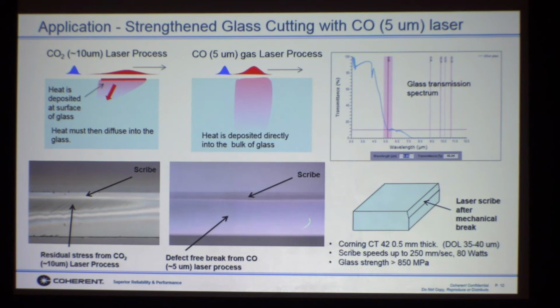These are some pictures of Corning, what everyone's calling Gorilla Glass. This is a very strong glass. The depth of layer is 35 to 40 microns. We're able to cut this at 250 or so millimeters per second with 80 watts. So this is not a real expensive laser, by the way. And you can see that it's perfectly clean, defect-free. And the glass strength, with the 4-point bend tests we've done, is all greater than 850 megapascals. So it's still very, very strong glass. That's one example of where CO lasers have an advantage by not absorbing so strongly.